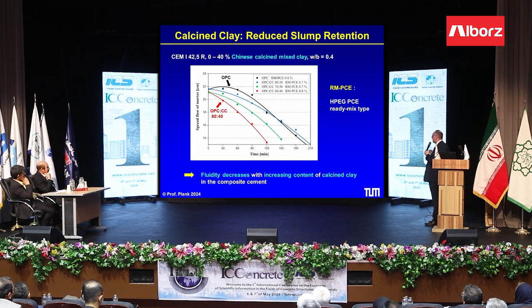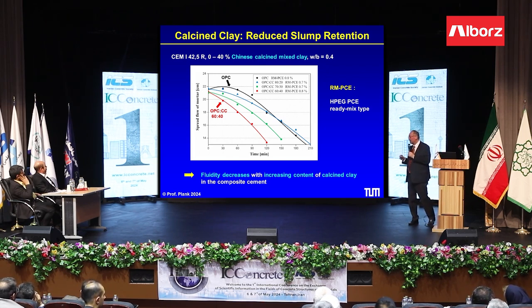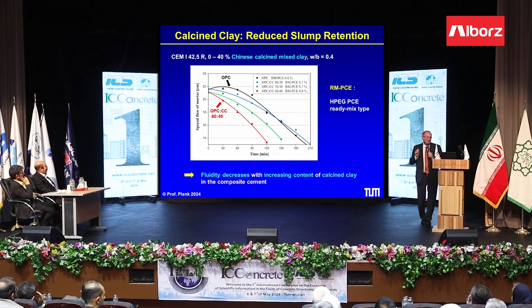Another problem of such calcined clays, which have a high metakaolin content, is that slump retention is very difficult to accomplish. The previous speaker mentioned this topic of slump retention and that we have different technologies, but all these existing technologies do not work in such a blended cement where we have, let's say, 40% of calcined clay with high metakaolin content. And we and other groups are working very hard on new admixtures which can give reasonable slump retention in those binder systems.